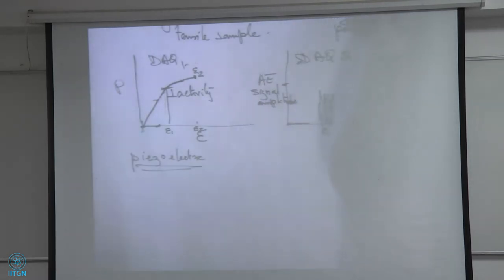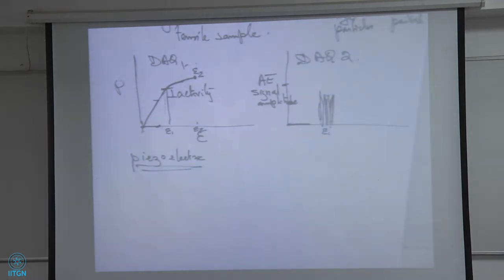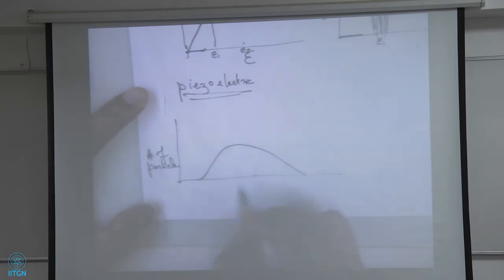And then when you go up in strain, let us say this is my epsilon 1. Here is my epsilon 2, where my first particles are cracking, the large ones are cracking, right? You remember I showed you a graph where large particles crack first, then the second particles. So I have a distribution of these, right? It's not just one size. There's a distribution of size, so this will be number of particles versus size.